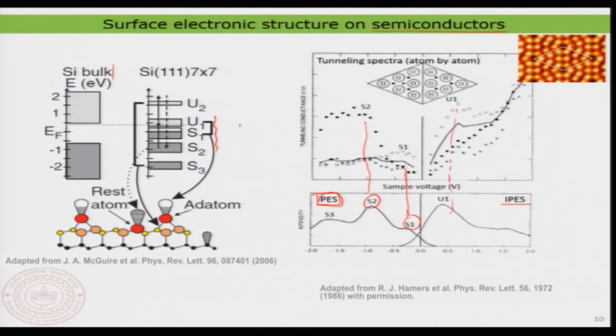There is slight variation in the energy, because in photoelectron spectroscopy you do collect things from a larger area. So, therefore, this averaging effect is there. So, this is what the techniques are when you compare scanning tunneling spectroscopy and ultraviolet photoelectron spectroscopy. One is extremely localized, so you can go onto an atom and then do the spectroscopy, and the other one gives you information about a larger area.